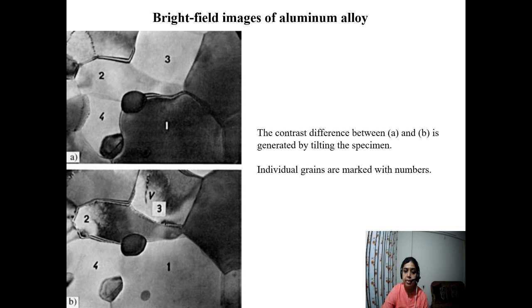Here again the contrast between A and B can be seen. Here it is bright, but the same is dark over here. So this is the difference. Why is this difference there? Suppose the same sample is here. We have just tilted the sample. This is the effect of tilting of the sample in the TEM machine. Once we have tilted the sample, the Bragg condition is disturbed. So whatever was being satisfied is not satisfied, and it is satisfied in some other area. Earlier this was satisfying for this, now it has changed for something else. It is completely destructive for this. So individual grains can be marked with numbers just by tilting the specimen by a few degrees, maybe even less than 1 degree. Just by tilting the specimen, different kinds of images can be obtained.